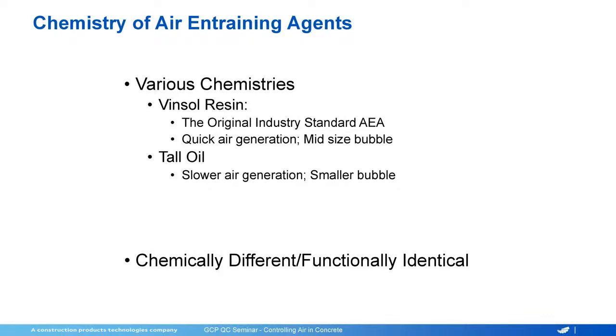So there are different chemistries. Vinsol resin, the original air entrainment, doesn't need as much mixing, gives you a decent bubble. Tall oils give you a smaller, tougher bubble, and take a little longer to mix.